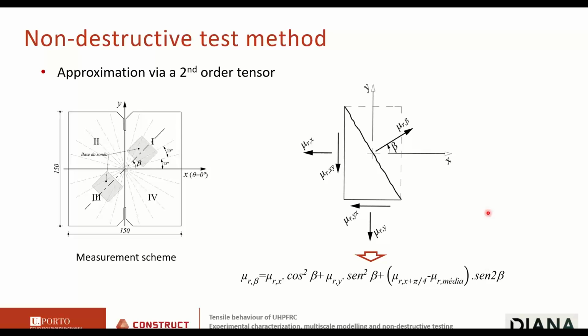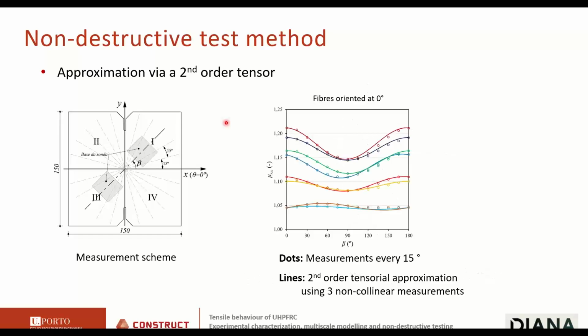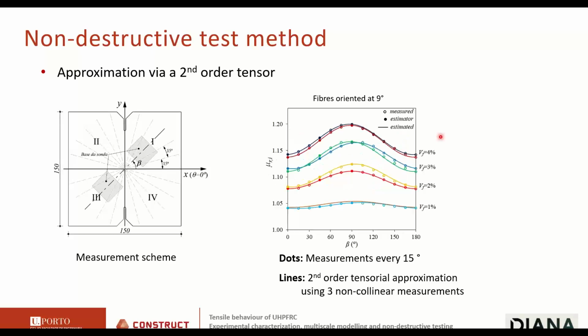The good thing also is that if you want to know the tensile strength along any direction, we can approximate the relative magnetic permeability by a second-order tensor, which means that we only need to make 3 non-collinear measurements. This is how the tensorial approximation compares with the measurements every 15 degrees. So the agreement is quite good.